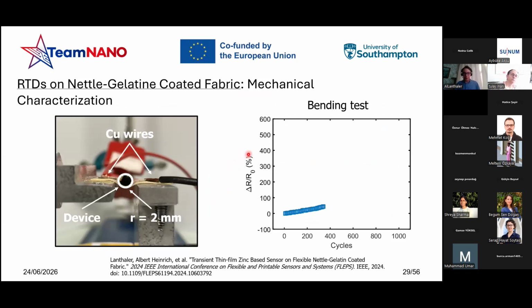As mentioned before for the previous device, it's very important to understand the mechanical characterization of this device and its ability to withstand mechanical bending. So what we have done, we decided to go for a more harsh characterization, down to a bending radius of 2 millimeters for 1,000 cycles. As you can see here, measuring the resistance relative to the flat condition, the resistance is increasing over time, but it was actually still conductive after the 1,000 bending cycles.